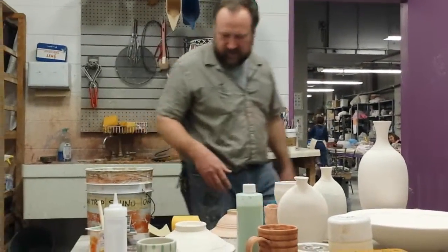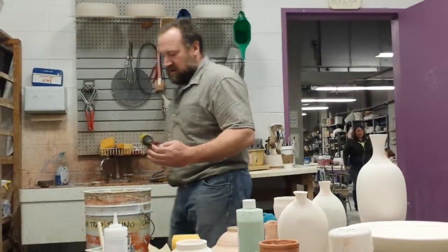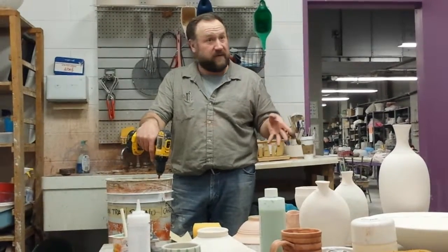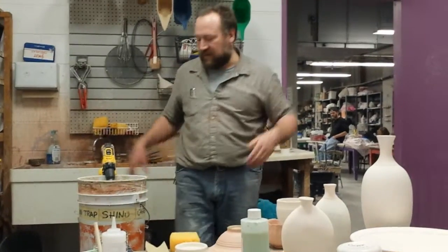The two shino glazes are really, really finicky when it comes to thickness. The carbon trap — the orangey one on porcelain is going to be real white if you get two layers on. You can see the second layer here on this grog stoneware — which has the most iron in it — it's still going to go pretty white. You can play with that: your first layer, nice and orange; your second layer, after it totally dries, you can go into a white situation.